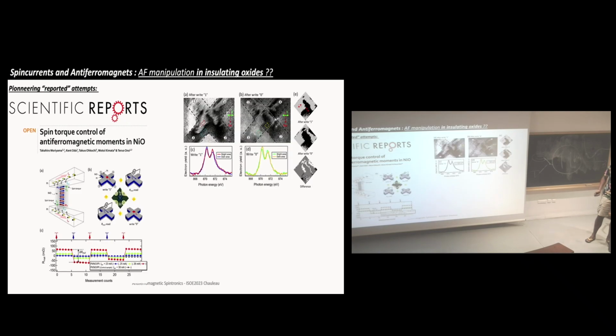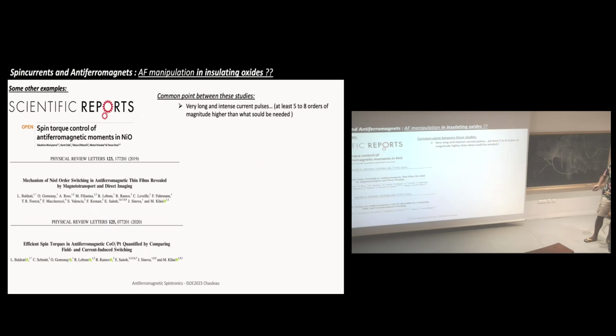I think this is one of the first ones, but one of the main difficulties here is that they were shining a very large current for a very long time. So nothing compared to 10 picoseconds. Basically, there was a huge amount of heat in this sample, and by looking before and after, they could see some change in contrast. So people got excited about this.